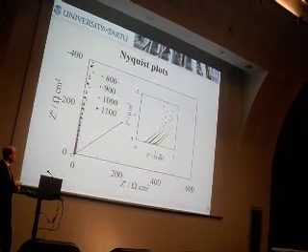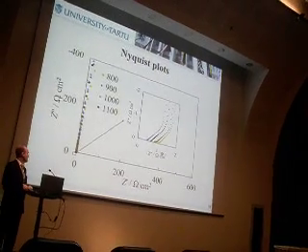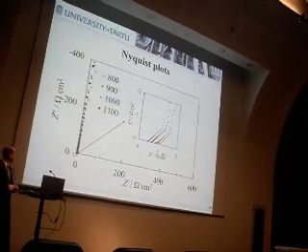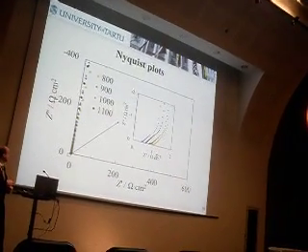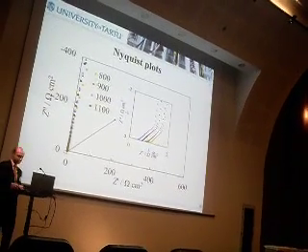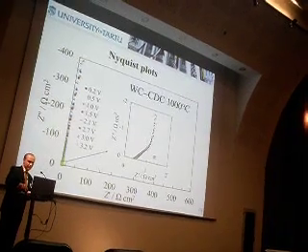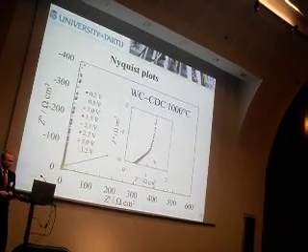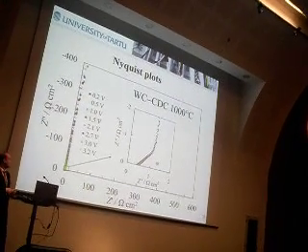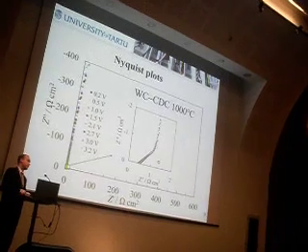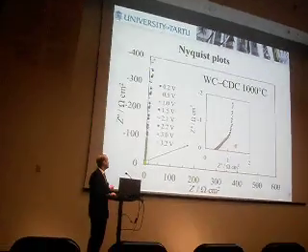They have quite low resistance in the high frequency area, and at the low frequency area the phase angle goes up to almost 90 degrees. And all these characteristics depend neither much on the synthesis temperature nor on the potential at which those Nyquist plots were measured.